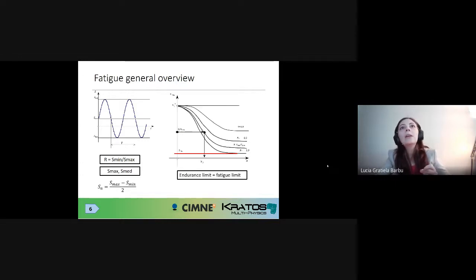Okay, now all of these cyclic loadings applied on specific components induce a change in the material properties. And these changes are recorded for a specific geometry by means of the stress-number of cycles Wöhler curves. What's important for me to explain to you is that there is no single stress-number of cycles curve. There is a whole family of Wöhler curves, where each specific stress ratio, for instance, has associated a specific Wöhler curve. So we can somehow understand the concept of SN curves as a smooth surface, okay, which varies with the reversion factor.